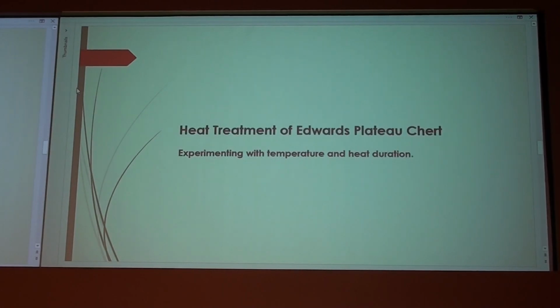So then I heat treated some Edwards Plateau chert. Now the thing with Edwards Plateau is sort of a generalized term. I mean, you can get Edwards Plateau, you can get Lampasas, there's some from Comanche County, and it's different, it's Edwards Plateau chert, but it is different. Some of it is better than others. I tried to keep the experiment with similar chert. There's one individual I get off eBay who pretty much sends a consistent type.